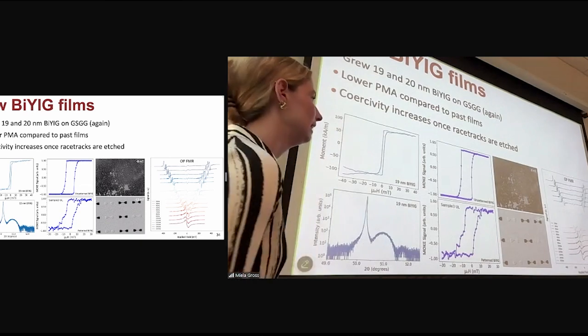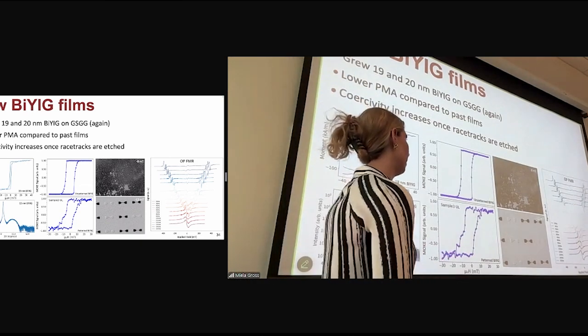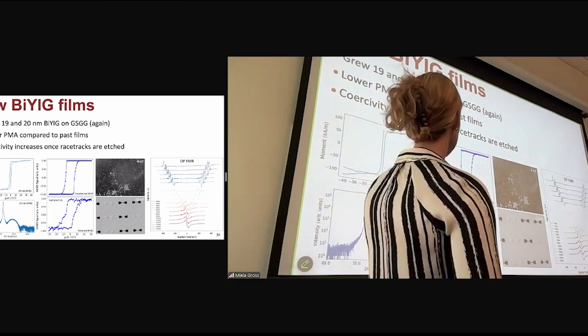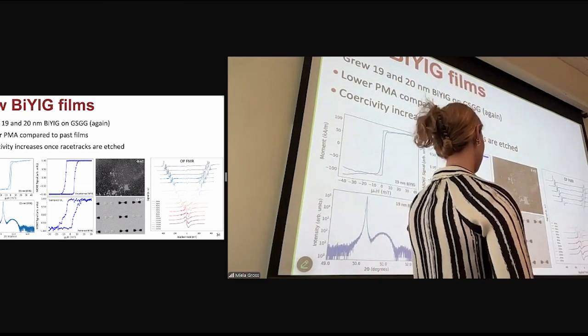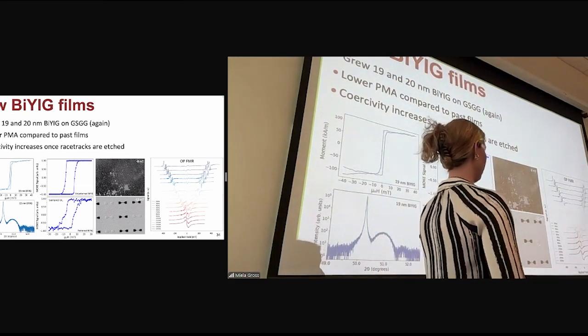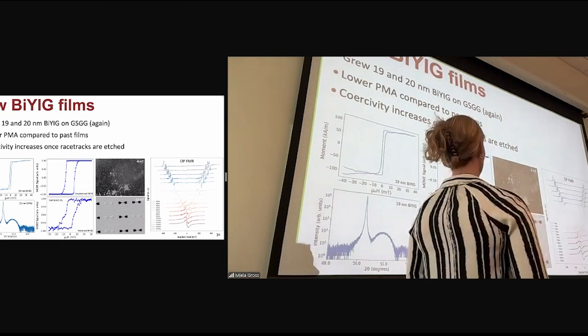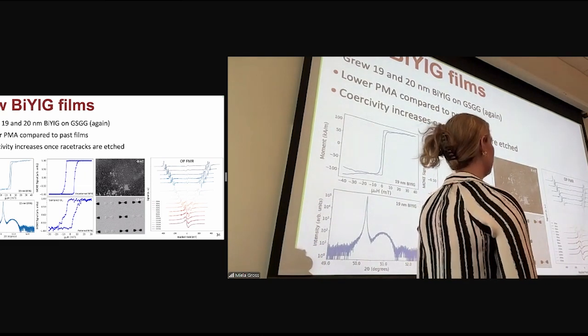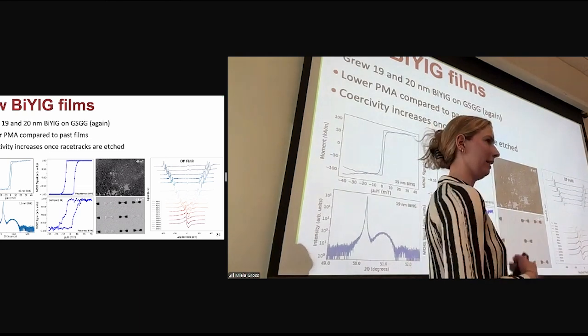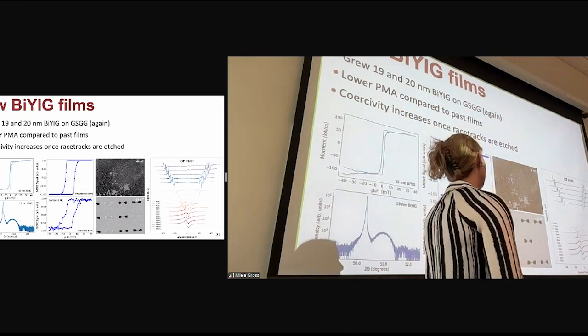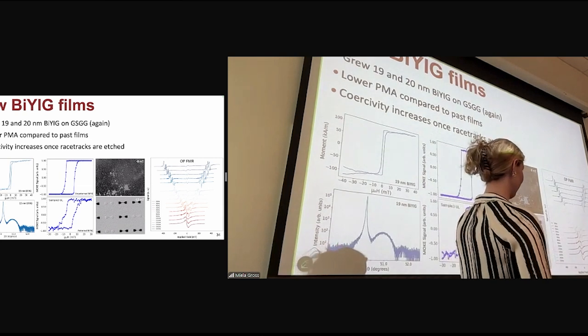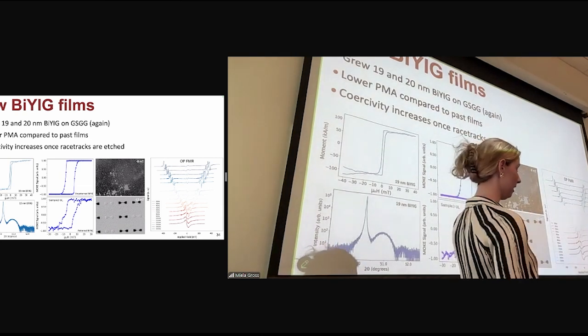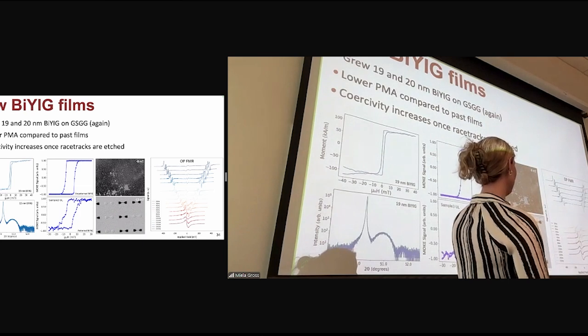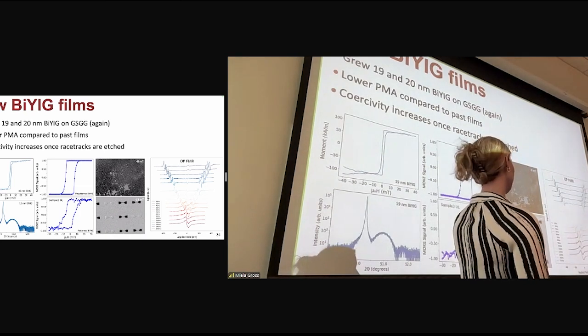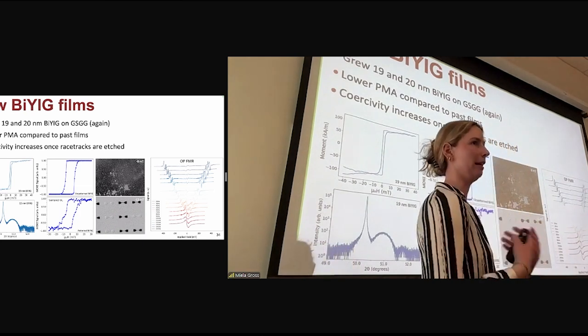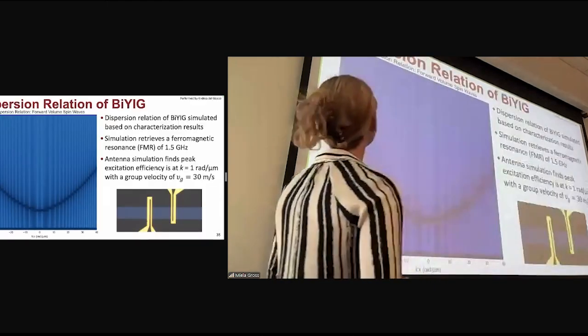And then I did some upgrades to our little MOKE setup, which allows us to find that the coercivity increases once the racetracks are etched. And so that's what these little pictures are showing here, or MOKE images is what they are. So at -8 millitesla on the bare film, the film is nearly saturated into the down state. However, if we apply -12 millitesla to the same film just after it was etched, only half of these little bow ties, these are our little racetracks, have flipped. So that's important for when we apply those small fields to our experiments.